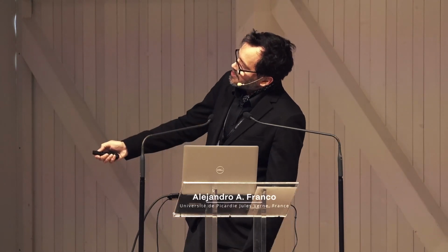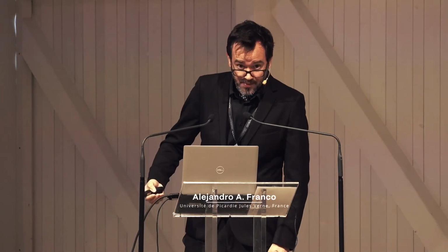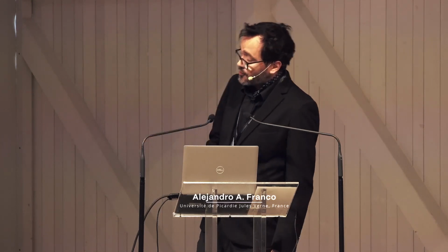need to apply in the calendering step in order to, at the same time, maximize the electrode conductivity, maximize the electrode density, maximize the active surface area, which is the area of contact between active material and pore filled with electrolyte, and minimize the tortuosity, which makes the electrolyte infiltration more painful, right? And which decreases the ionic conductivity. That's why you want to minimize the tortuosity. This is a multi-objective optimization problem that can be solved thanks to the combination of these tools.